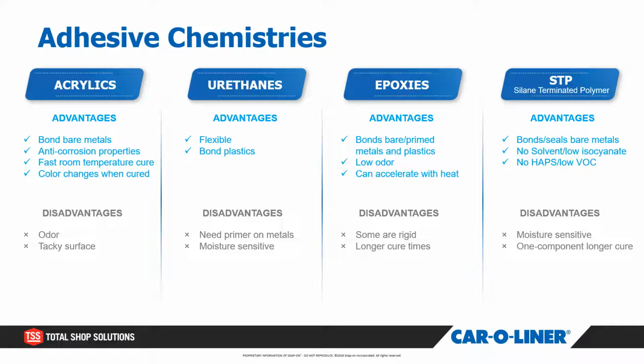What some of the disadvantages are: they can be very rigid and they have longer cure times. I know when the E60s came out, it was the first time that we actually rolled a car into a paint booth to bake it. And that was a big adjustment, trying to roll the car around the shop and get it into the paint booth and bake it. By baking the epoxy adhesive, you just accelerate the cure time, and it actually creates a little bit stronger of a joint.